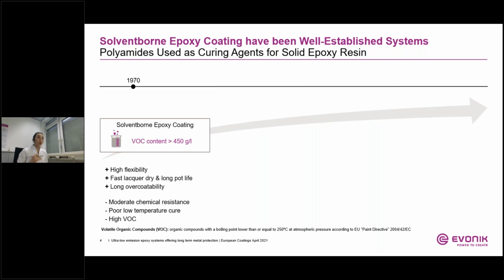But polyamides also provide excellent pot life, allowing spray application for up to 6 hours when used with solvent-based solid epoxy resin. This normally results in coating formulations with a VOC content greater than 450 grams per liter. VOC stands here for volatile organic compounds.